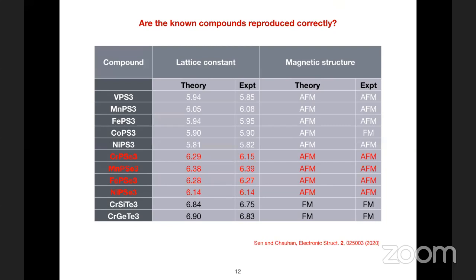Okay, so how are we doing on the known compounds? As you can see, the lattice constants and the magnetic states are reproduced well for the known compounds, except this one, cobalt phosphorus sulfide. We still end up getting a ferromagnetic state. Now, I cannot get into the details of this, but we have a work, you see the reference below, in which we have discussed how to describe the correct magnetic ground state of some of these compounds in DFT. So cobalt phosphorus sulfide is something we still need to explore more, but the others we are able to reproduce correctly. And just to let you know that prior to this, there were a couple of papers, at least in the literature, which failed to describe the correct magnetic ground state of these compounds.